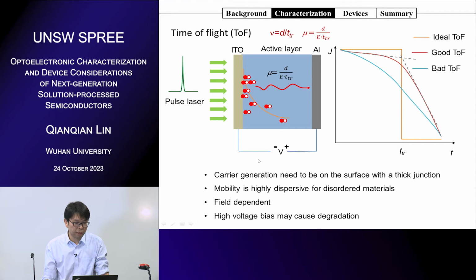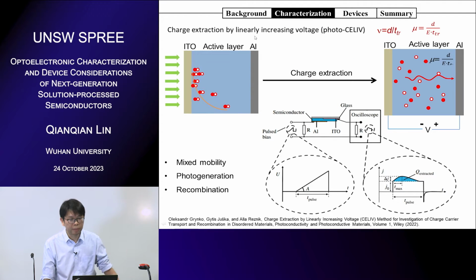And TOF measurement is also very dependent on the field or the bias voltage. And normally, a high bias voltage is required for the TOF measurement. It may cause film degradation for some organic materials or perovskites, because at high bias voltage, perovskites can have ion migration, and it will affect the real measurements. So this method works, but mostly for really good samples, like perovskite single crystals or thick films, but not for very thin films or those with very dispersive charge transport. Then people later on developed new methods to overcome these drawbacks.